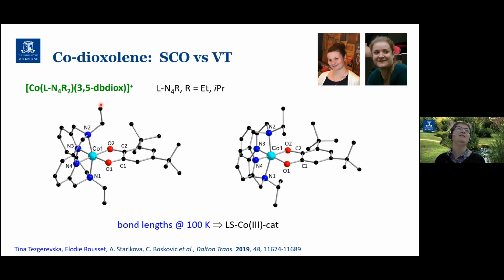So you can see here, there's the analog with the ethyl substituent. Here's the analog with the isopropyl. We made those cobalt complexes with a 3,5-ditertbutyl-dioxolene. Now, crystallography is really useful for us in VT chemistry because those of cobalt-dioxolene systems, at least, because those bond lengths are really indicative of the oxidation state and the spin state.